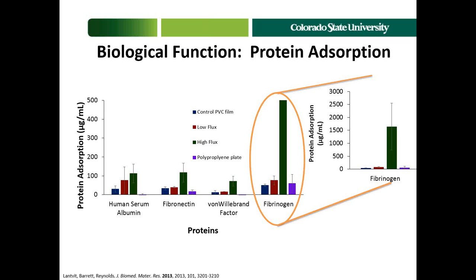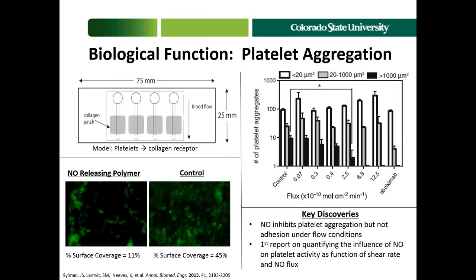What we found, though, is that this fibrinogen is then no longer active to participate in the clotting cascade. In other words, platelets will not bind to the fibrinogen and therefore not become activated, therefore rendering a surface that then will not clot. And we know that we've isolated the effect of nitric oxide rather than the other materials parameters based on our extensive sample preparation method as well as characterization on the surface.